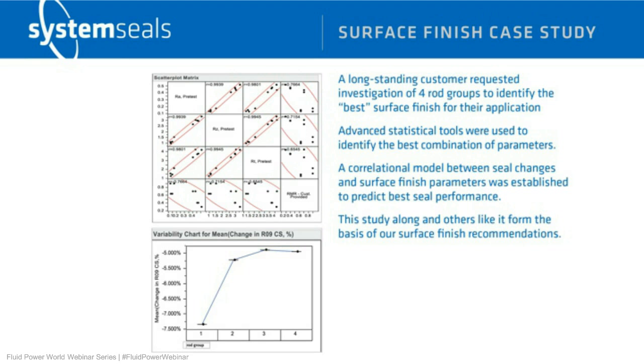So let's take a look at an example of some research that we've performed. In this particular case, we had 4 groups of surface parameter combinations that we were investigating. And again, we found that those 4 that we were investigating were statistically significant. That's why we see these nice tight bubbles. They're effectively lines that are telling us that there is a linear correlation between these parameters and the leak and wear characteristics that we were measuring.